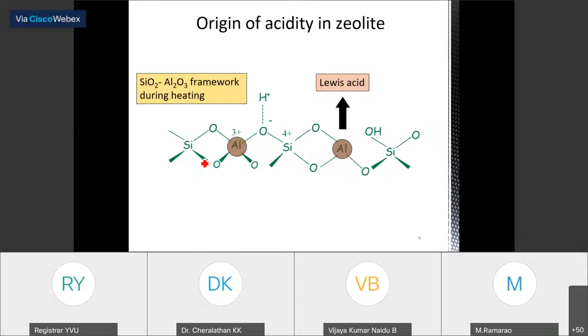When you heat this framework, which has silica and alumina, and you break this bond, you will have a tri-coordinated aluminum, which is similar to that of AlCl3. It can act as a Lewis acid. So in a zeolite, you can have Brønsted acid sites as well as Lewis acid sites. That is why these materials, zeolites, are attractive acid catalysts.